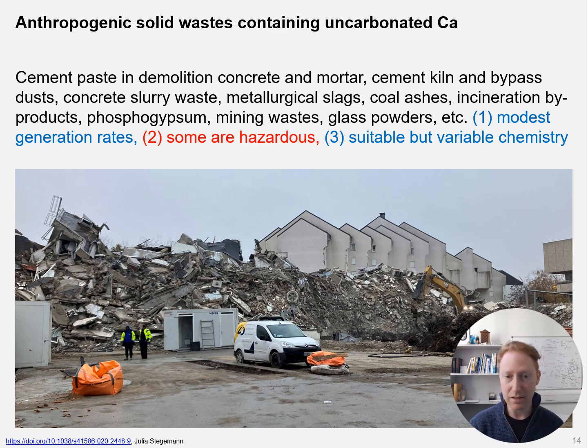On the other hand, some of these materials have suitable but variable chemistry. For example, steel slags can contain high calcium content, but they can also contain variable contents of heavy metals like chromium and manganese, depending on the source of the steel scrap used to produce the slag. And this may make them undesirable for some concrete materials applications because those heavy metals may not be reactive, but it also represents a loss of valuable alloy metal content, which could be better used to make new steel rather than concrete.